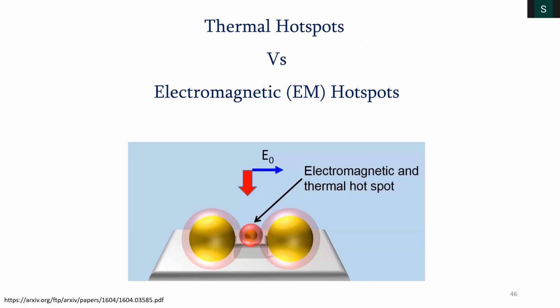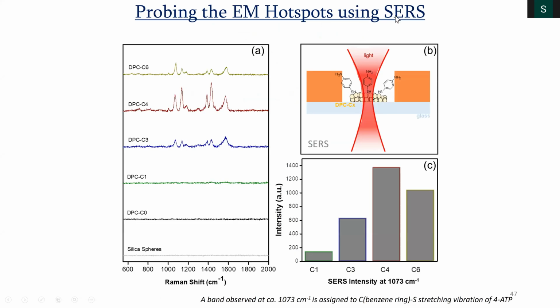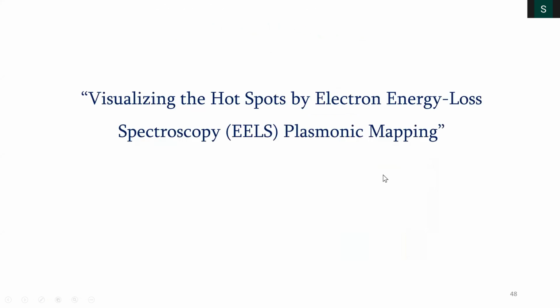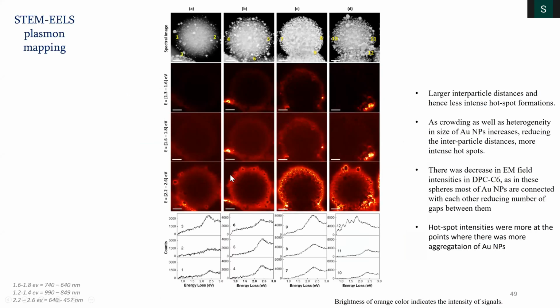QA session. So in addition to the thermal hotspot, there is also the electromagnetic hotspot, and we also wanted to know which material has more electromagnetic hotspots. For that, we did SERS, surface enhanced Raman spectroscopy, and we observed that C4 again has the highest number of electromagnetic hotspots. We also tried to visualize these hotspots by electron energy loss spectroscopy, and we see that when the gold particles are going closer and closer, the brightness indicates the energy and the intensity of those hotspots. So it's more in the C4.